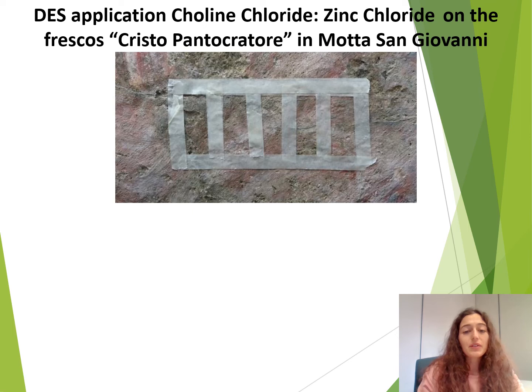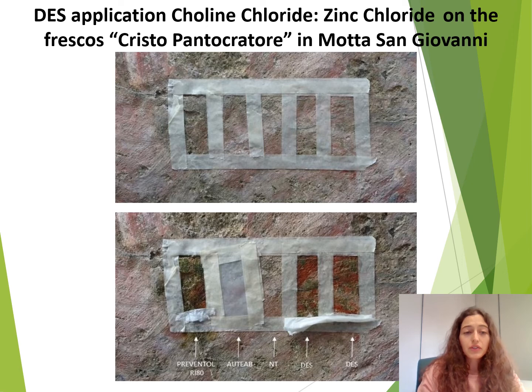Choline chloride zinc chloride was applied during the conservation treatment of the fresco Cristo Pantocratore in Motta San Giovanni, Reggio Calabria. Choline chloride zinc chloride was applied to the paint film. After application, a reduction of biological patina and no microbial growth with the passage of time was observed.